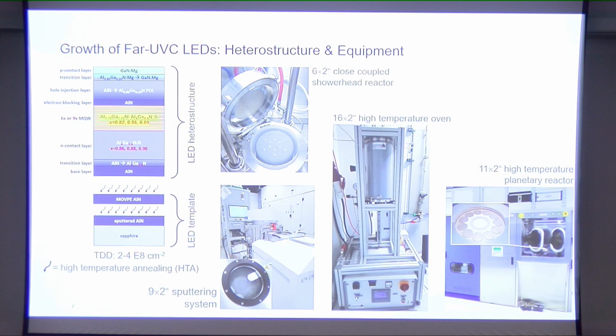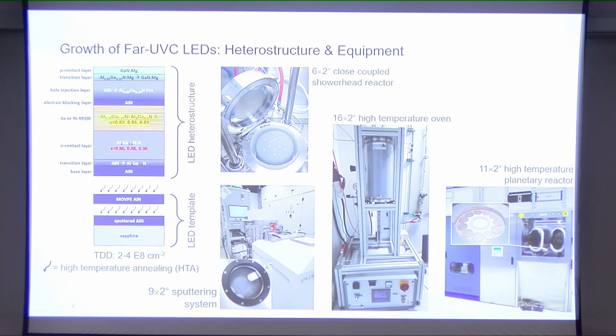And here you can see this is a real LED structure that we are using for our far-UVC LEDs. We basically divide our growth into two parts. At the bottom we have our templates, which is sapphire and aluminum nitride, and then we have an LED heterostructure on the top. For the templates, we are using an aluminum nitride sputtering system, which you can see here. It's for nine 2-inch wafers, and then we have a 16 times 2-inch wafer high temperature oven to anneal the sputtered aluminum nitride layer, and then we regrow using MOVPE another aluminum nitride layer on it using an 11 times 2-inch planetary reactor. And then for the LED heterostructure, we use a 6 times 2-inch close coupled showerhead reactor for our system.